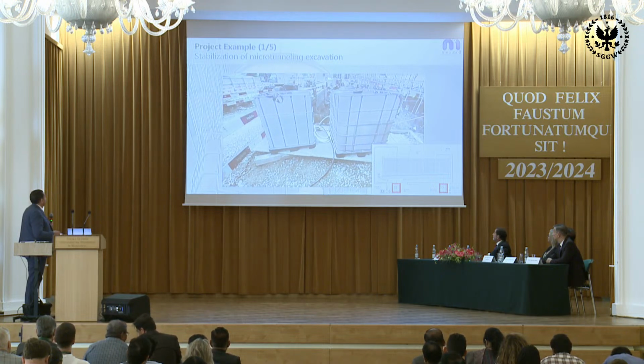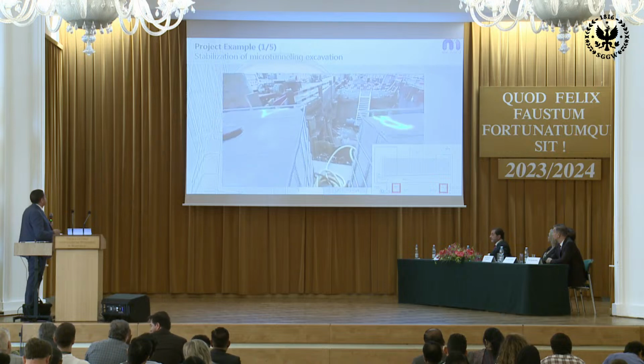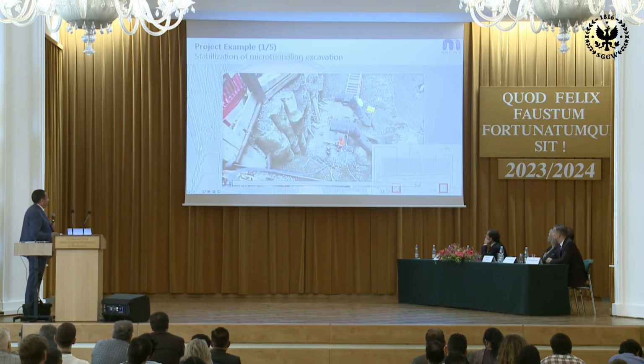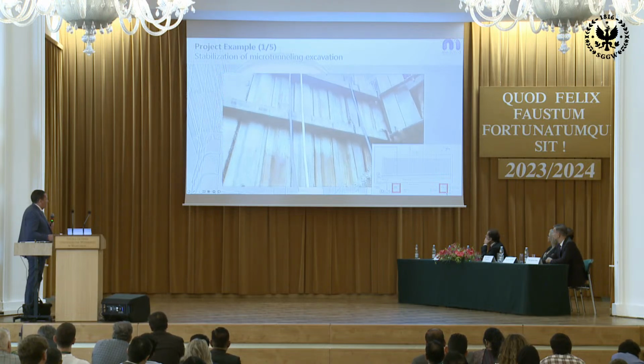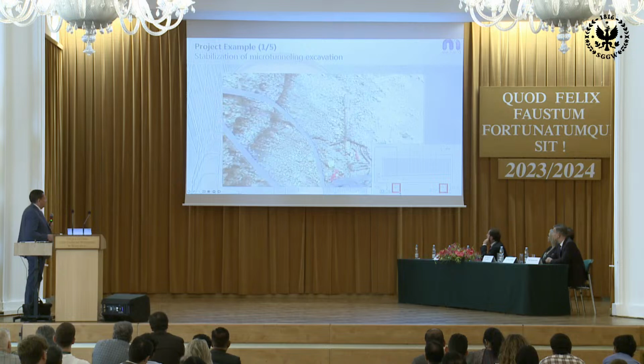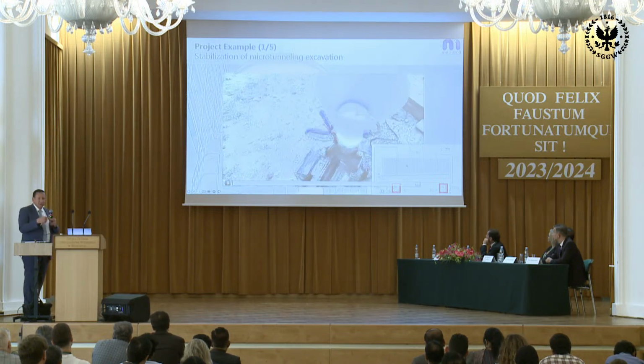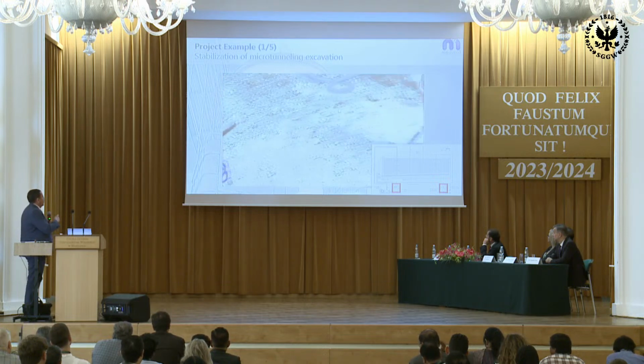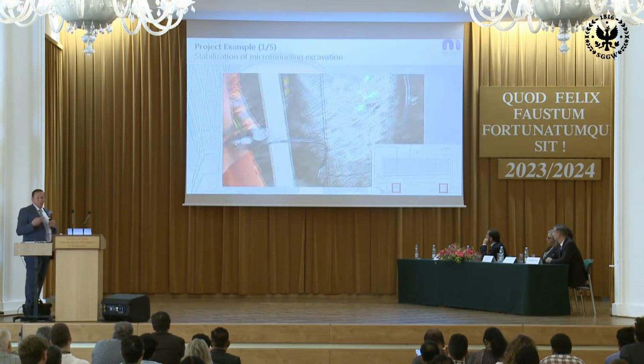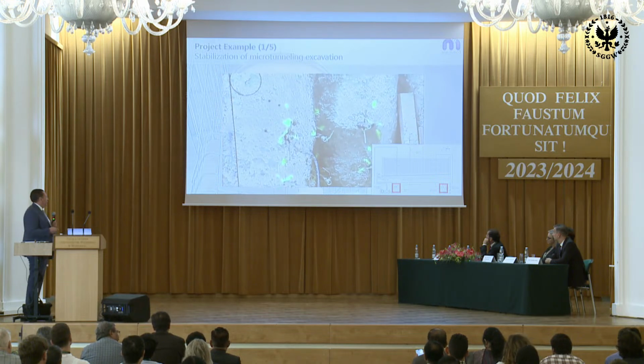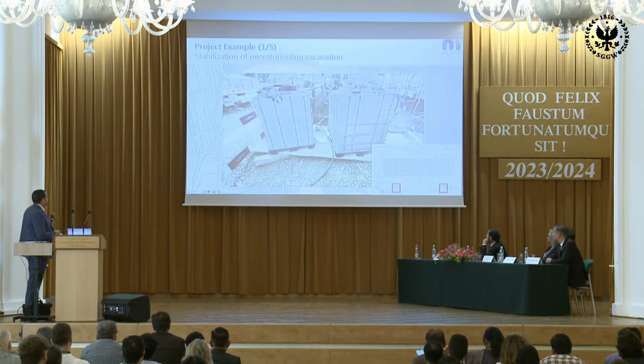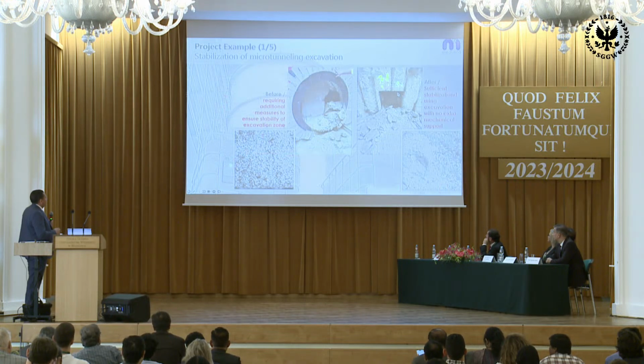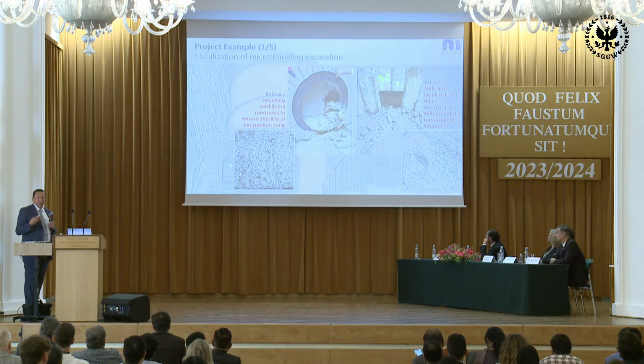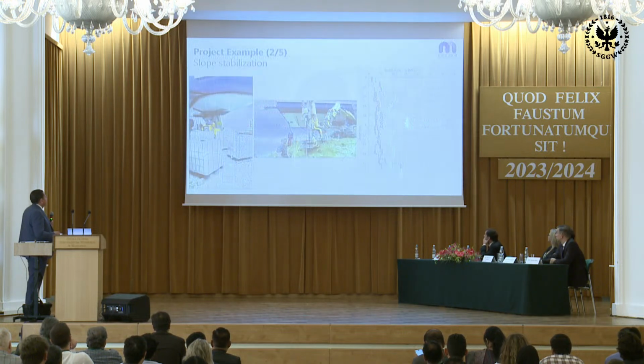So let me show you some examples, quickly, 5 examples. First one, stabilization of a micro-tunnel excavation. As I was mentioning, each time we have calcium coming from one side and our solution from the other, and we inject them together, and the precipitation happens in the ground. We use very simple technologies. For instance, the pump doesn't need a lot of pressure, it is 1 bar of pressure that we inject in the ground, as you can see. Basically, with the requested precipitation of the calcite in the ground, we were able to stabilize an area that initially the microtunnel would not be able to move through without reinforcement. So this is a way to show how it's performing well.